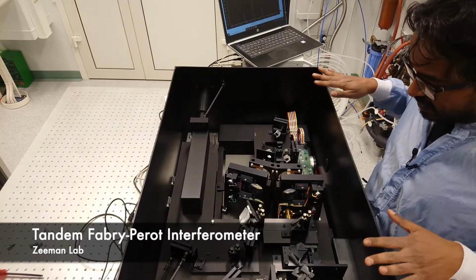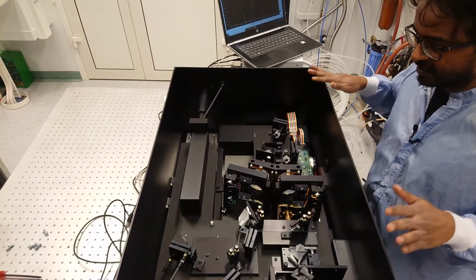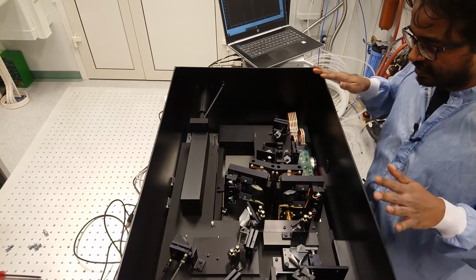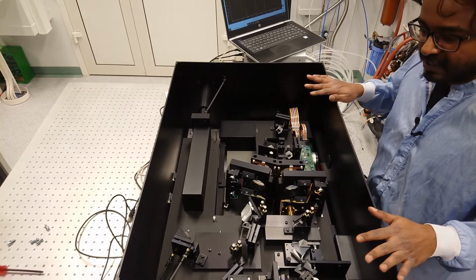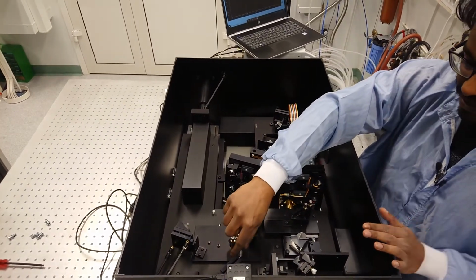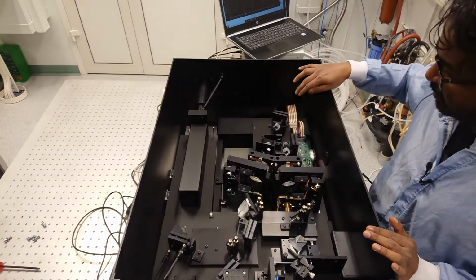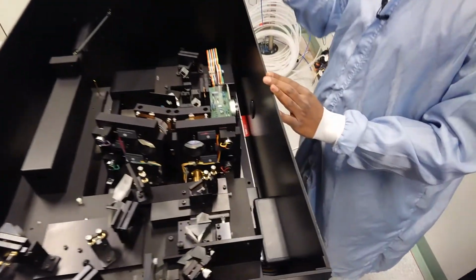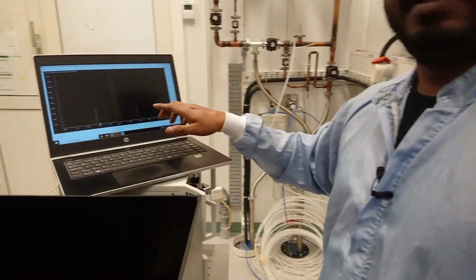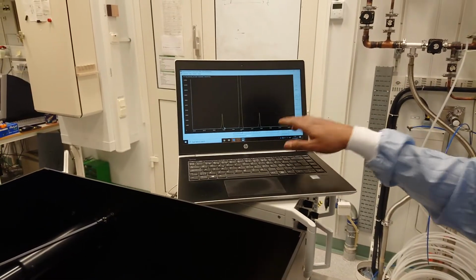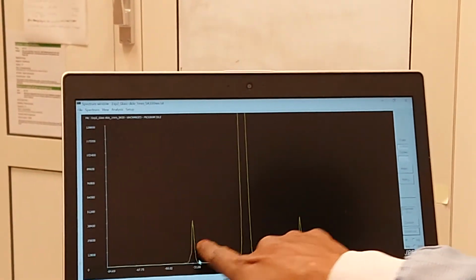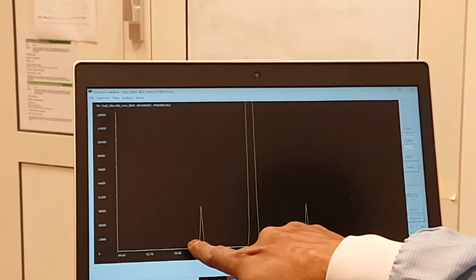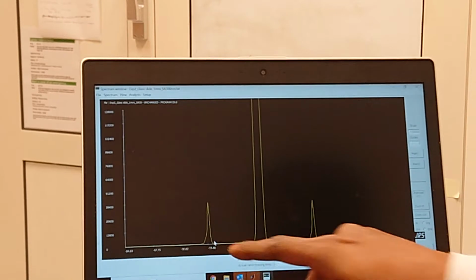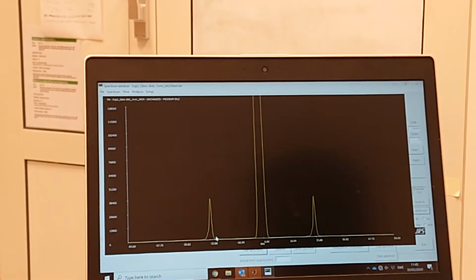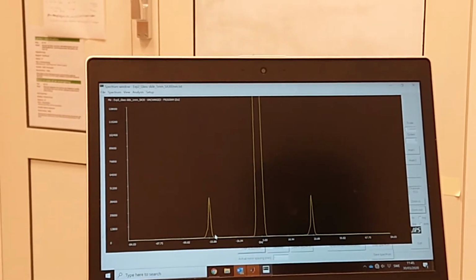So what this interferometer does is two things. It has high contrast, and it is highly selective in its spectral regime. So after the signal reaches this, it enters the interferometer. An example of data that we collect is shown here, and these two are the Brillouin shifts, and this is the laser line. So we use these Brillouin shifts to measure the acoustic wavelengths, acoustic velocities, and in turn get the elastic constants of the material.